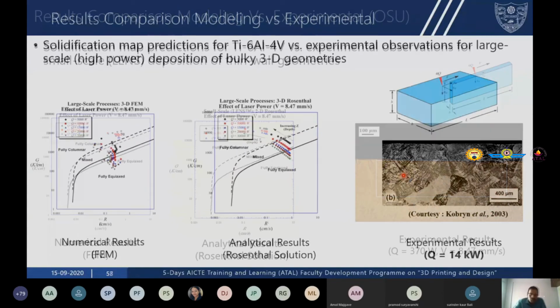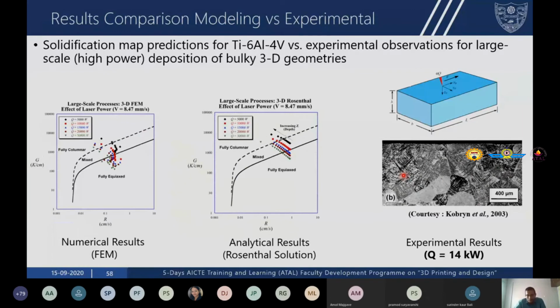Now this shows the results for a high power process where you are using higher powers, somewhere around 5,000 watts to 30,000 watts, or 5 kilowatt to 30 kilowatt. Here again, this is for plate geometry, because generally we don't use this level of powers for a thin wall geometry. So this is the numerical FEM results, this is the Rosenthal results, and this is the experimental observation, which shows a mixed morphology.